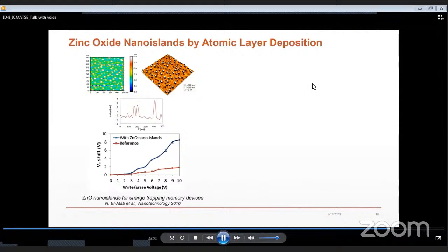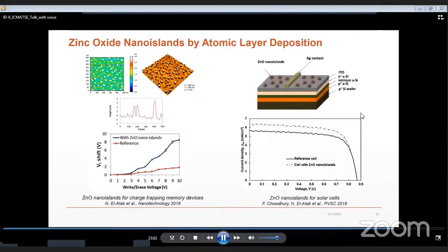In addition, a much larger memory window was achieved with the islands compared to the case with the thin film, due to the increased density of oxygen vacancies in the islands, which are obtained due to the growth mode. I have also shown the application of the islands in solar cells in collaboration with a colleague. In this case, the islands enhance the light trapping and increase the current due to photon energy downshifting. So here the islands absorb the large photon energy and emit a photon with a lower energy, which then gets absorbed by the silicon solar cell and therefore enhances the current.